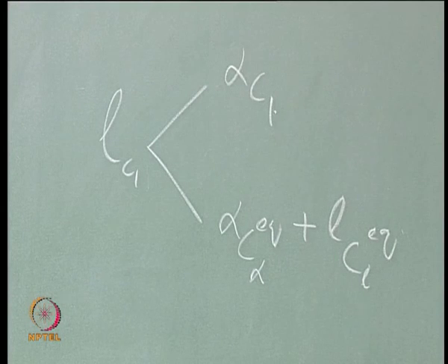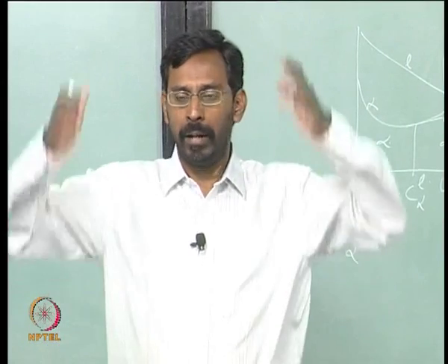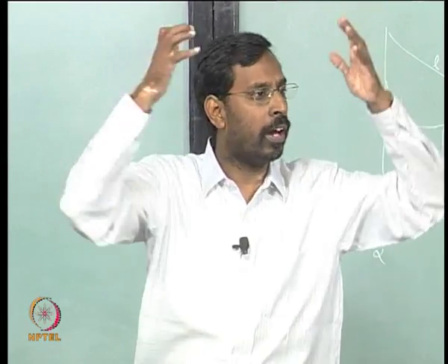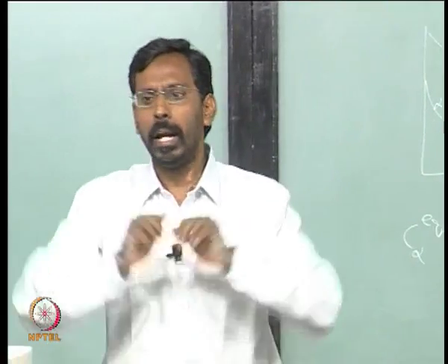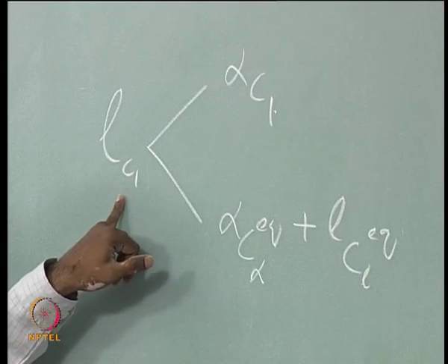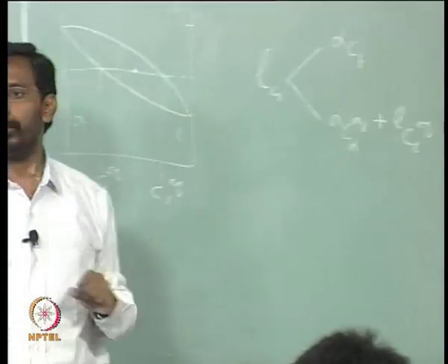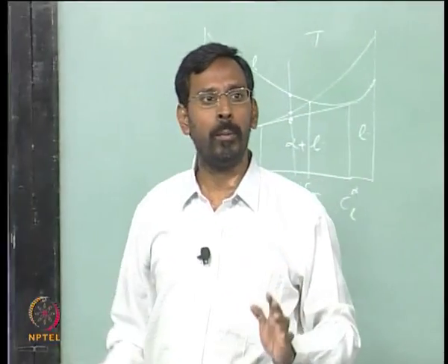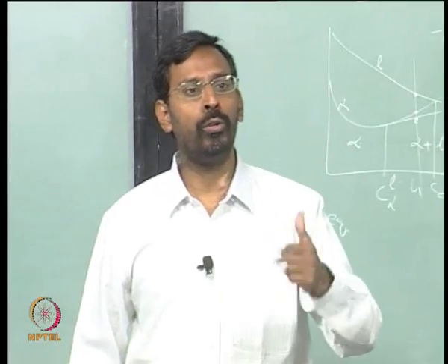that means we call it partitioning taking place. Okay, that means the B atoms which are there inside the liquid get partitioned between alpha and liquid, and that is how you get alpha having a different composition from the starting composition, and liquid having a different composition from the starting composition. This would come out provided you are close to equilibrium.